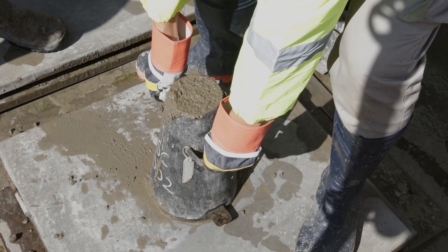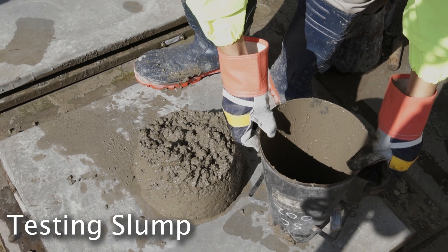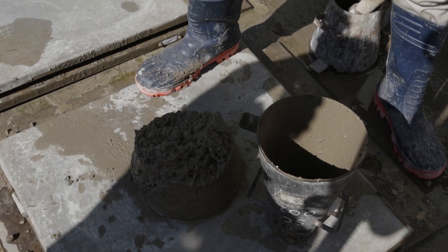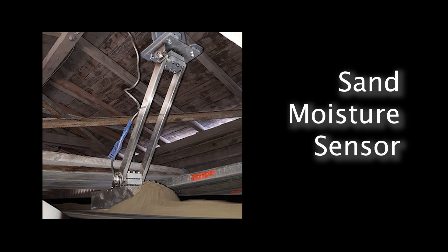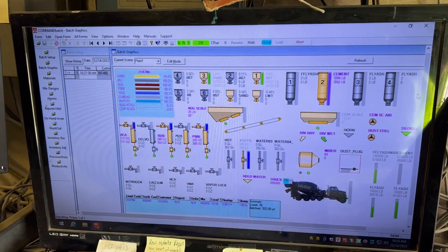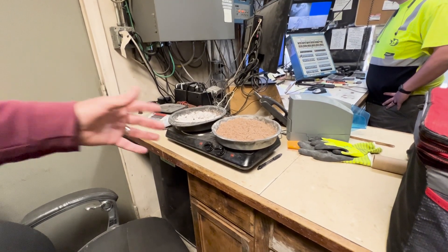The amount of water in the mix is critical to its slump — meaning how easily it flows — and its final strength. Since the sand and the gravel are stored in the open, their moisture content can vary considerably. How much water needs to be added depends on how wet the sand and gravel are. To account for this, there are inline moisture sensors that let the operator and control system know the moisture content of the incoming sand and gravel. These moisture sensors undergo calibration checks twice a week to make sure they are reading reliably.